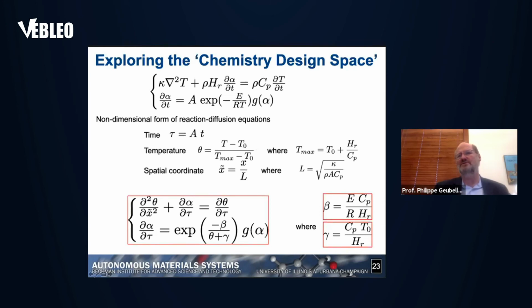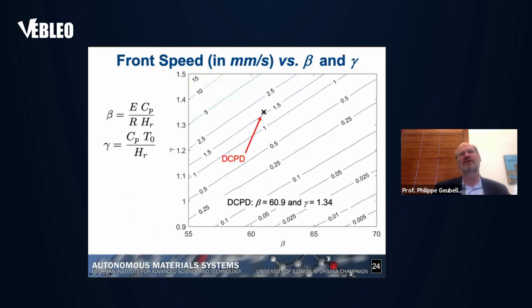The two parameters that I denote by beta and gamma: the first one denotes the effect of the activation energy that shows up in the Arrhenius term, right? And the second one corresponds to the initial temperature of the resin. And so we can actually use this kind of approach to extract the full solution within the plane of these two non-dimensional parameters, beta and gamma, which are repeated right over here.